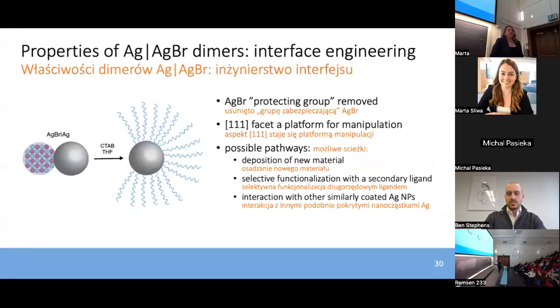So I just showed you evidence for how the interface between the silver and silver bromide phases of that dimer impacts the plasmon resonance of the silver nanoparticle. Now, in seeking to even more deeply understand the nature and impact of the interface in the system, we sought to controllably manipulate the environment around that silver nanoparticle even further and focused on the 111 facet that made up that interface in the dimer morphology that we know is now bare or accessible.